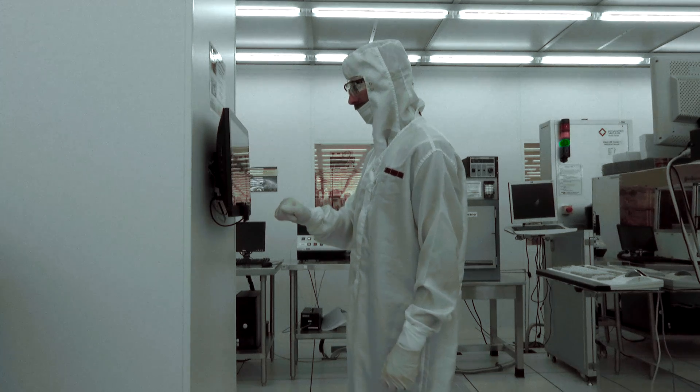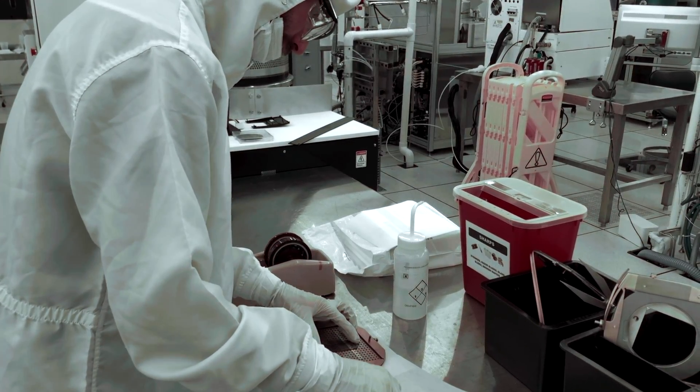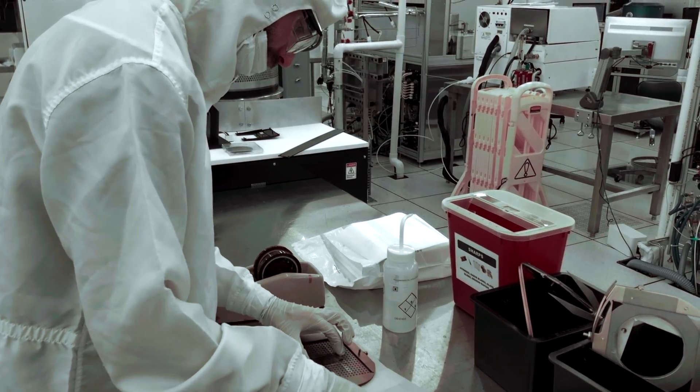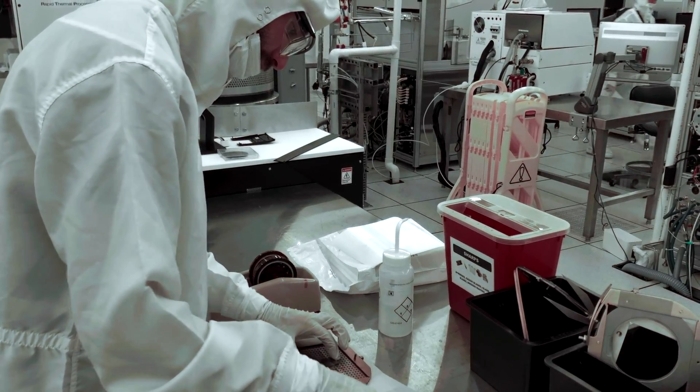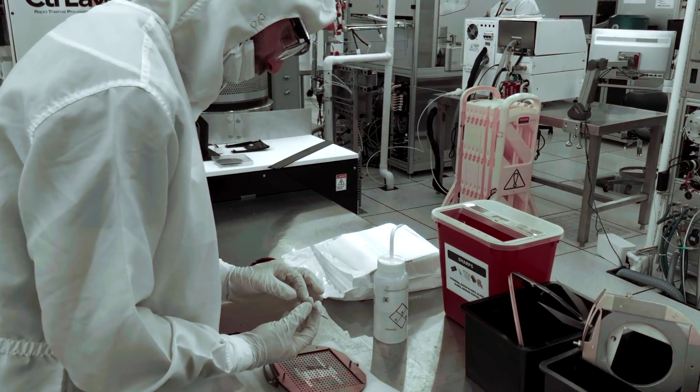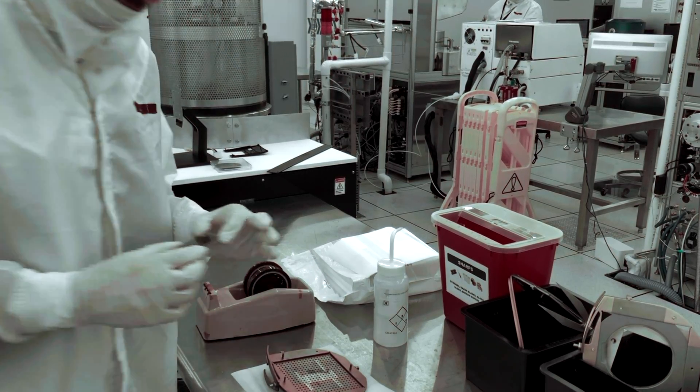Note that platinum and gold source metals need to be weighed before and after each process. Minimum weight for platinum is 30 grams and minimum weight for gold is 25 grams.